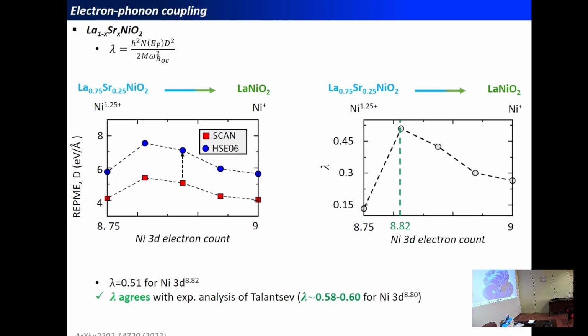And what's amazing is that the computed lambda with our model has a value around 0.51 for this nominal valence of the nickel cation. And this lambda does agree with the experimental analysis of Talantsev, which identifies that lambda in this system should be around 0.58 to 0.60. And so within the crude approximation we are making, we are able to reproduce the nice trend and the nice value for the optimally doped nickelates.